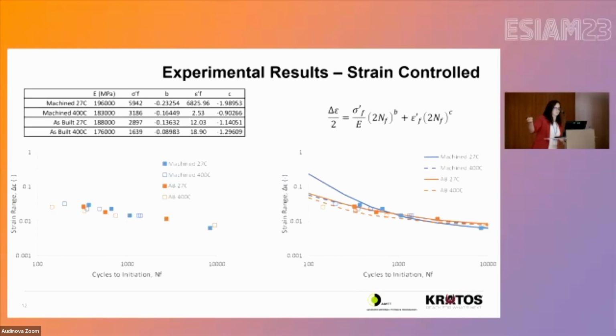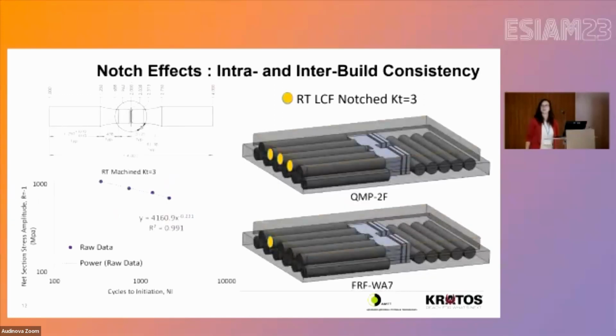So at room temperature, you get this response, and at high temperature, you get this response, or at room temperature as built, you get the same response as the high temperature, which is interesting, but most important for our situation. It shows that we are coalescing to a single solution, to a single understanding of what happens to our material, which is important because what we're trying to say is we're consistent, right? But that's great. You did a bunch of smooth specimens. You said your part has notches in it. Okay, cool. We made a bunch of notch specimens.